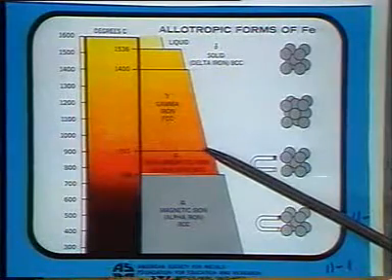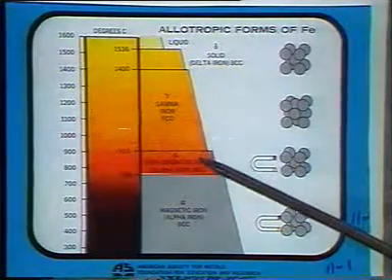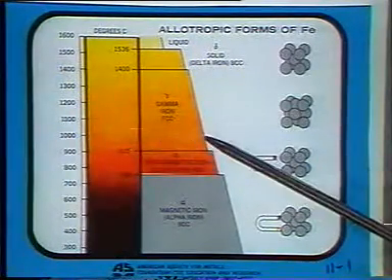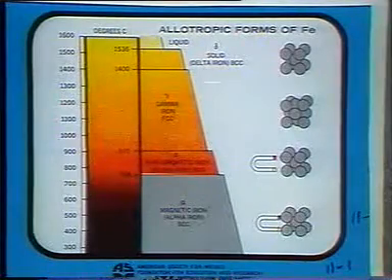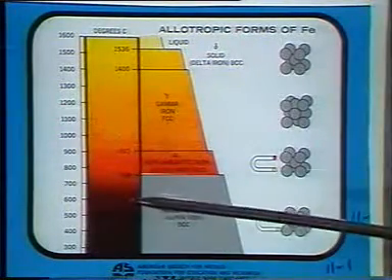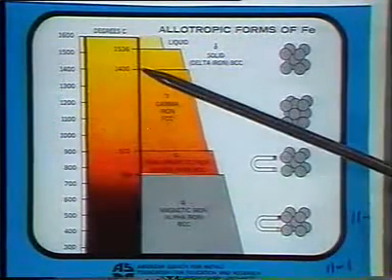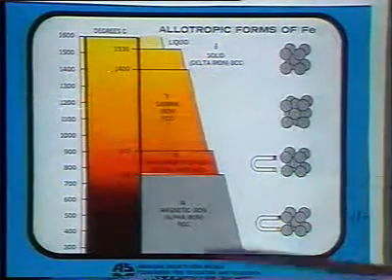And if you looked at that, it would be a cherry red. And when he got it to that temperature, he knew it was ready to quench, and he quenched it back into the water. Actually, if he'd heated it on up, he'd gotten into the delta region of body-centered cubic again, which would be up in here. Actually, he's transforming the material, and here's what he's going to see if he transforms the material.